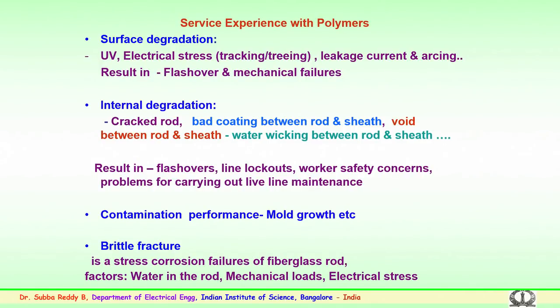So, the bad coating also could cause internal degradation over a period of time, or the voids, small air pockets between the rod and sheath, could lead to the air pockets getting discharged, the charge build-up, and also failure because of the insulation becoming weak at those junctions, where these small air pockets could break down. The water entering these places could, in case there is microstructure damage to the fiberglass rod, form acid, which could contribute to the failure through internal degradation between the rod and the sheath.